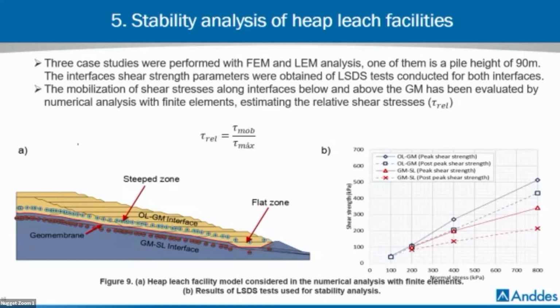So the mobilization of the shear strength along the interfaces below and above the geomembrane has been evaluated by numerical analysis to estimate the relative shear stress in each interface. The relative shear stress indicates the proximity of the mobilized shear stress to the shear strength of the failure envelope, or the maximum shear strength. With this expression, you can understand the relative shear stress. When we are close to 1, it's possible that the shear stress is near the peak value, and it's possible to exceed this value, and we can use post-peak shear strength in our analysis.